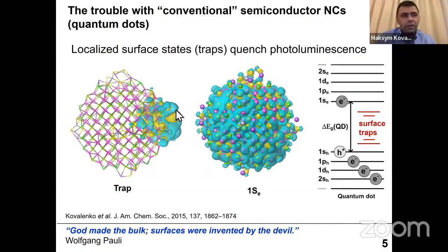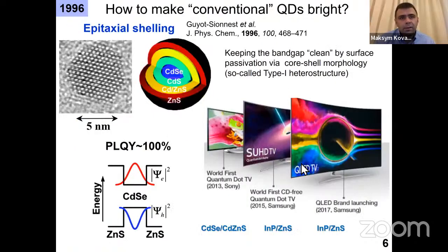And the reason for that was the surface which quantum dots have. They have a very high surface to volume ratio. And the surface is basically made of dangling bonds. Basically, you cut the lattice, you create dangling bonds, so orbitals which are neither binding nor anti-binding. And so they are mid-gap states, right, which exist localized on the surface. And they are capable, even in a very small quantity, of quenching an electron or hole, thereby preventing efficient luminescence. So what people have done since very early on, they focused on how to resolve this